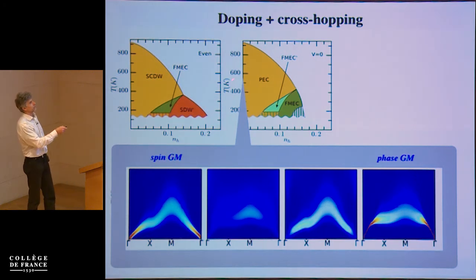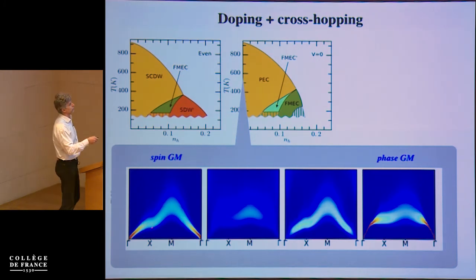So now let's say we are at this point. So if we have this gauge symmetry, so if the cross-hopping is 0, we have two Goldstone modes. We have this one, which corresponds to the breaking of the spin rotational symmetry, and we have the phase Goldstone mode, which corresponds to the breaking of this gauge symmetry.